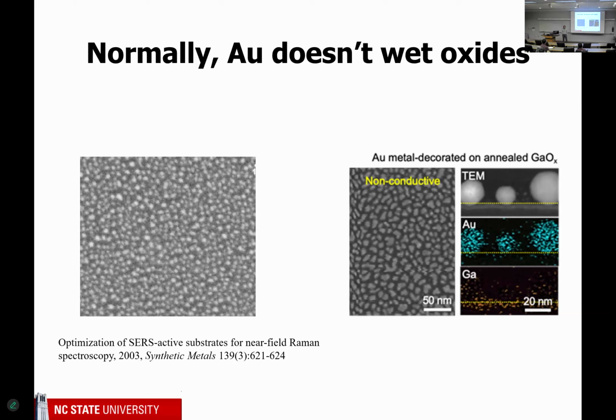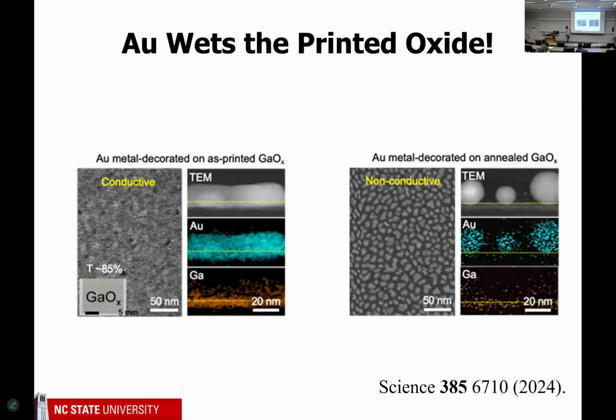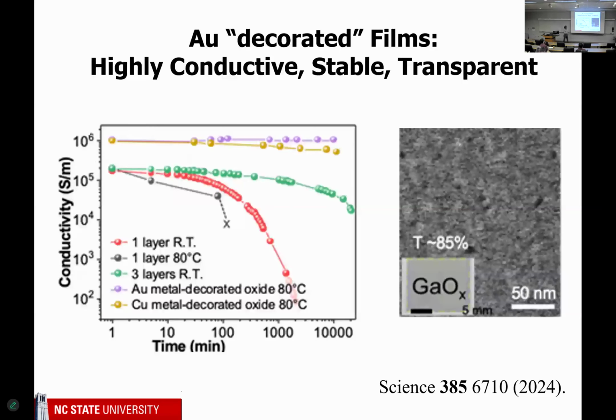But on our printed oxide, we print it fresh and then we deposit gold. This is what it looks like. Not islands, it's uniform, it's transparent. You can see this is gallium oxide, the word gallium oxide printed on a piece of paper, put behind our film. It's transparent. But the main thing is compare the way the gold looks here, continuous film, versus there, little islands.